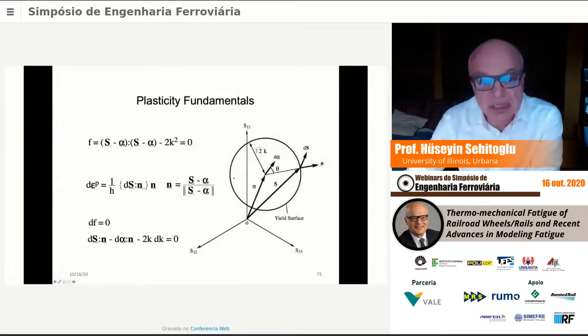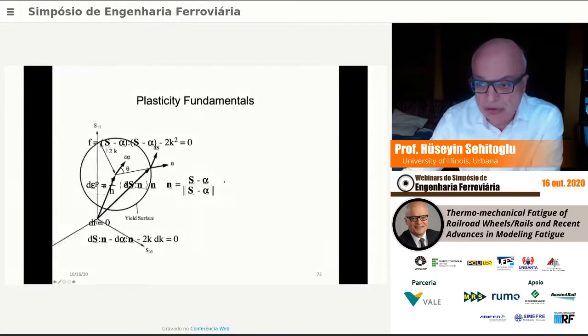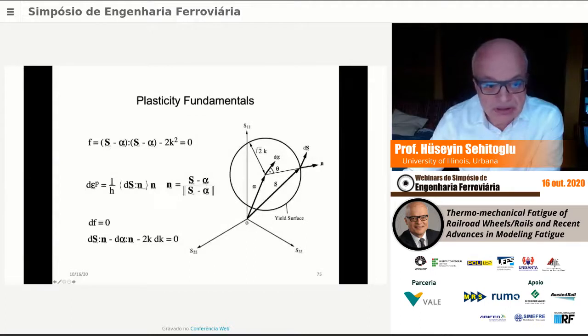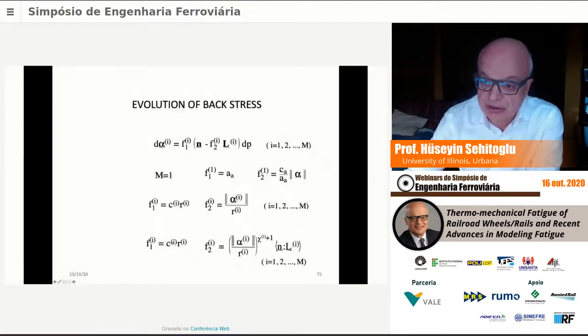The plasticity fundamentals: that's the yield surface, that's the back stress, that's the deviatoric stress, that's the yield stress in shear. This is the normal to the yield surface, and that's the direction of the plastic strain. And the evolution of the alpha is very important, and typically it's taken to be along the direction of the normal to the yield surface, but in reality it is not. Experimentally, one can verify that it is not. This is a consistency condition.